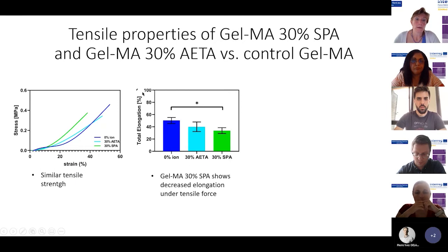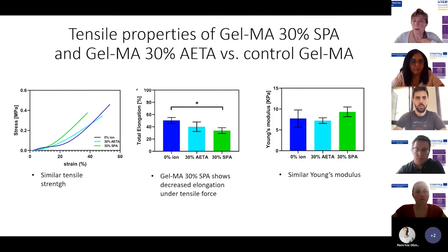And then if we look at the total elongation, this means that if you use the same force on the gel, how much does it elongate? And then we do see that the elongation is larger in the standard condition, so in the GelMA condition, versus the conditions with the SPA ions. And then the Young's modulus doesn't change over the three conditions. There was no statistical significance.